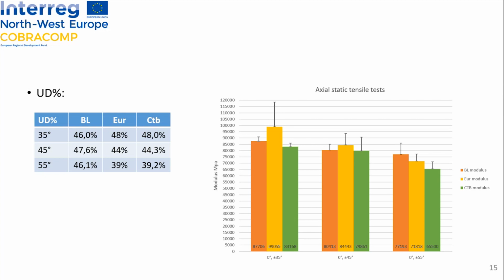The first graph shows the modulus of the coupon tests in axial direction. You can see that the rigidity of the coupons is close at 35 and 45 degrees. But at 55 degrees, the UD fabrics and biaxial braid, so the baseline materials, bring better results compared with the triaxial monolayer and multi-layer braids. It can be explained by the UD ratio, seen in the table here, which is lower for the braid structures, and also maybe by the waviness of the UD and bias yarns.